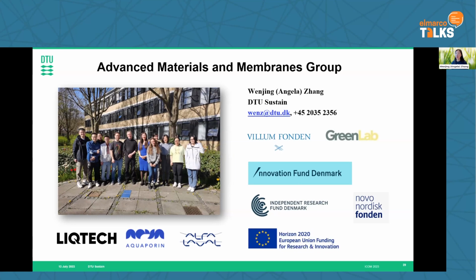Thank you. We have a couple of questions coming in from the audience. One question is, do you think that functionalizing the nanofibers will affect the porosity of the scaffolds? Yes, certainly. But I don't think it will change dramatically. Often the growth of the functionalization on the fibers is very thin around the fibers. So it will change the porosity, often reduce it, but it will not sacrifice the porous structure of the nanofibers.